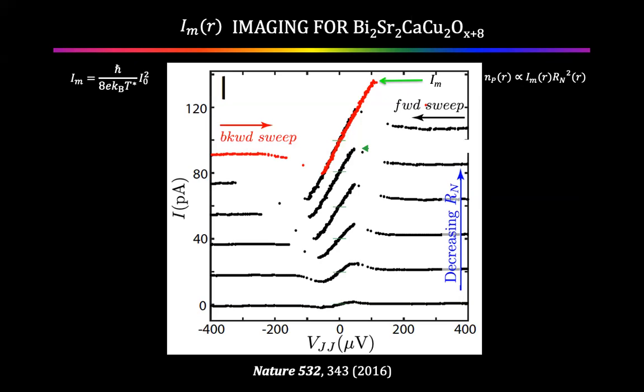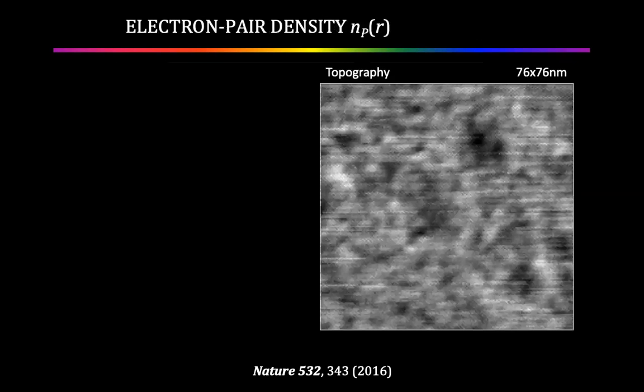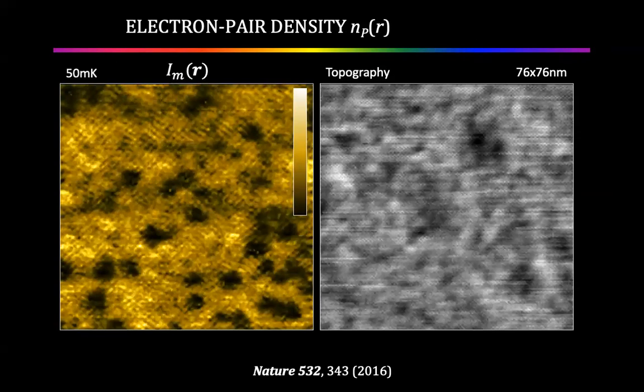All right, so now we're going to measure this maximum in the pair current at microvolts in this field of view with a tip that we know to be a D-wave superconducting tip from the single particle spectrum as a function of location. It looks like this. This was one of the first images ever made of the condensate, probably the first image ever made of the condensate in a cuprate superconductor. And it looks pretty hairy, actually. There's a lot of action in there. A lot of strange and unexpected things happen.